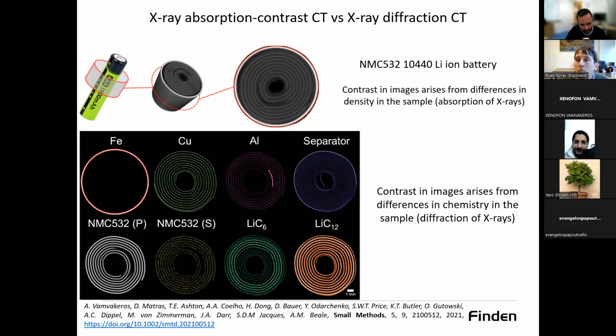You can see here that it is very easy to see images from just a 2D cross-section of our cylindrical cell, right? We can see our current collectors. We can even see the polymeric separator that is transparent in conventional X-ray CT. We can look at our cathode, or positive electrode. This was an NMC 532, and in this case, we noticed the presence of a secondary phase, which is not possible through absorption tomography or microtomography, and that was an inactive component in this battery, as well as different phases of the lithiated graphite.